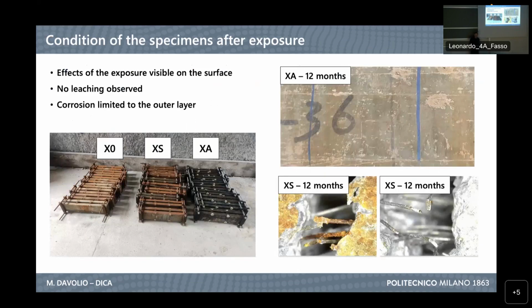material. The observed conditions of the specimen after the exposure, this is after 12 months for all the cases, we can see some differences from the three exposures, but this is just on the surface. And after cleaning the specimens, for example, for the geothermal exposure, we can see that there is no leaching on the surface, which is a very common phenomenon for ordinary concretes. And for chlorides, since we have corrosion, usually we observe the inner parts of the material, and here on the outer layer we have some corrosion, some rust on the steel fibers, which is not the case for the inner layers, thus meaning that chlorides did not penetrate deeply inside the matrix.